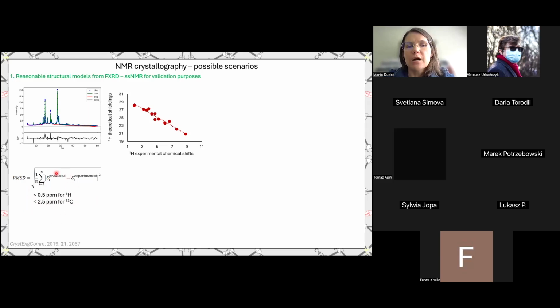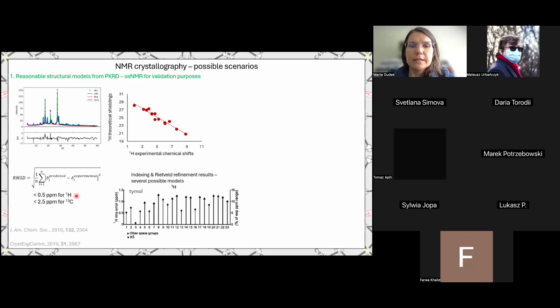Those values are, of course, from benchmarks. So if you take a crystal structure determined by single crystal X-ray diffraction, calculate the NMR parameters and compare them with experiments, you will get an agreement below those values, definitely. So this is how it works.